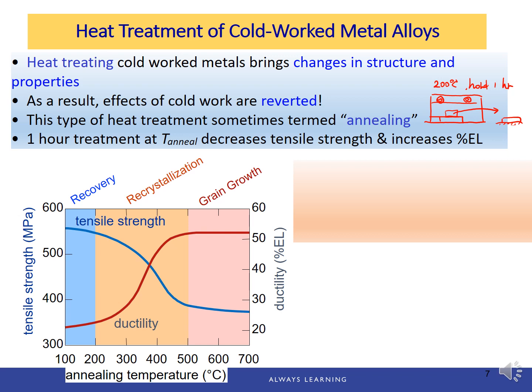Here's one example or plot of the annealing process for a certain material. I believe this is a brass alloy. After 1 hour of treatment at different anneal temperatures, the result shows the tensile strength and ductility of the material at different annealing temperatures. So for example, at 200 degrees Celsius here, after we put the metal into the furnace for 1 hour, after annealing is done, the ductility increased from this point here to this point, and the tensile strength decreases.